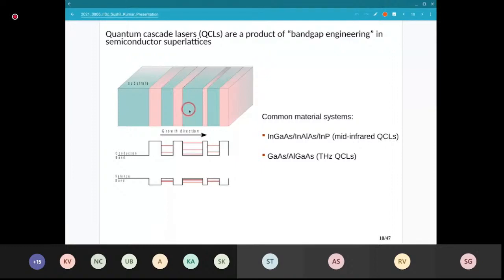Transport cannot be done, but we can do some basic estimation based on experience and also some basic calculations with the Schrodinger Poisson solver. Typical layer thickness is from a few nanometers to about 15 to 20 nanometers for each well and barrier. So these are nanometer layer scale thickness devices, and this structure is grown for almost a whole day to achieve a thickness of 10 micron in the end.